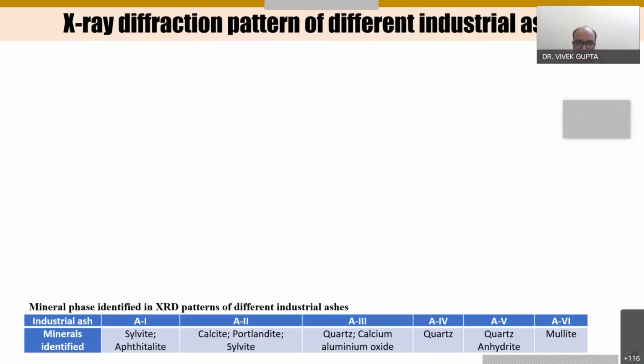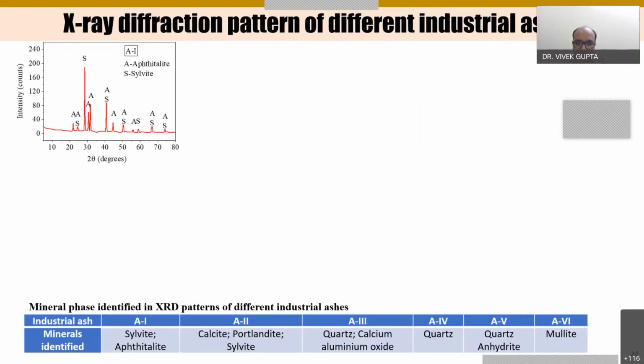So we have analyzed the XRD patterns of different ashes, and we found that in the A1 ash, sylvite and aphthitalite minerals, then A2 calcite, portlandite and sylvite minerals. Then A3, A4, A5 and A6 are the coal-based ashes.